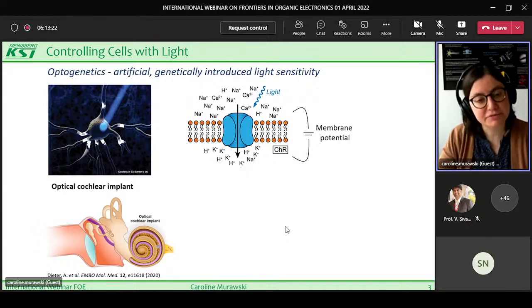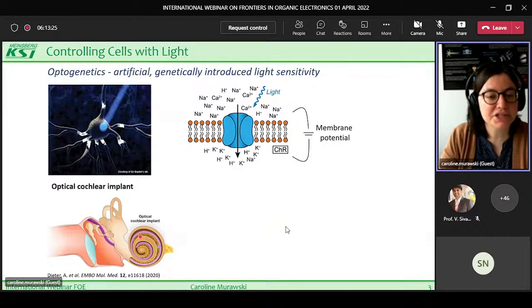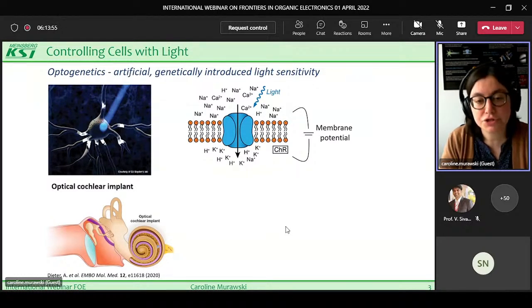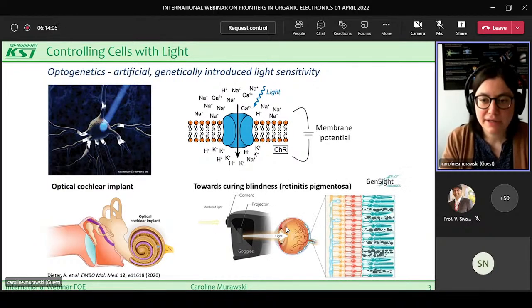But the problem, as I said before, with the electrical impulses is that their stimulation is very broad. So the signal spreads over many micrometers, up to millimeters, and therefore it's hard for them to distinguish between the low and the high frequencies that we can hear. And the optical cochlear implant instead can focus light much more into only a very narrow frequency regime. So the idea is that with an optical cochlear implant, it may be possible in future to restore hearing functionality with a much greater precision than what is possible with the electrical implants. And I want to touch just one other example.